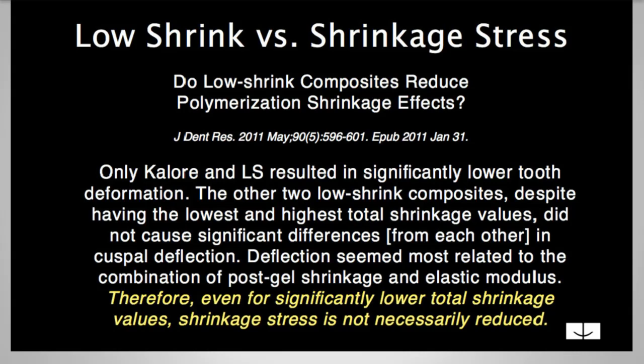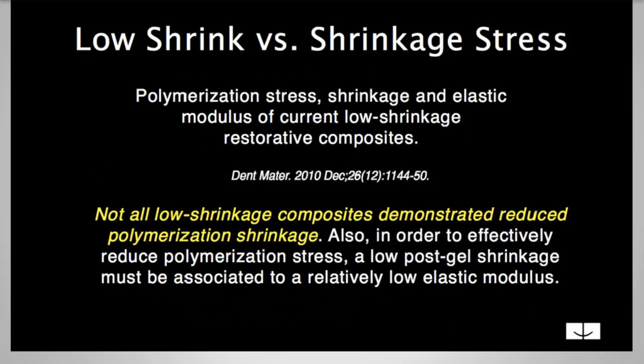Here's another study that was done saying the same thing, that not all low shrinkage composites demonstrate reduced polymerization shrinkage. It's really about the elastic modulus. That's much more important in understanding the shrinkage stress. So when you're thinking about a composite that you're doing and how you're packing it and how you're curing it, which one you're using, you want one that has low shrinkage stress, not just low shrink.